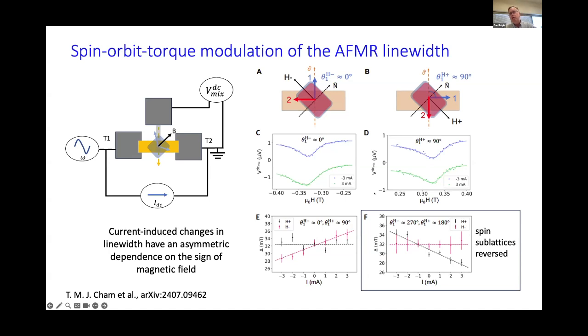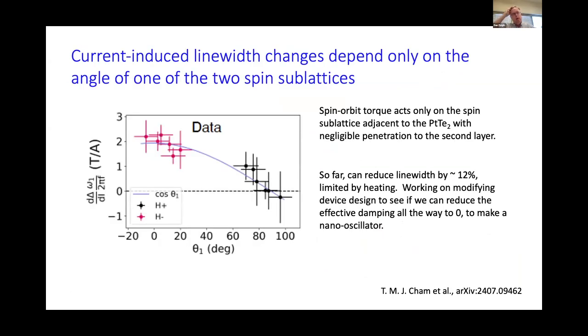And with the magnetic field, we can also switch the direction of the spin sublattices. If we do that, we see the opposite effect, the asymmetry in the magnetic field switches sign, as you'd expect from this picture. So we can look at how strong the current effect on line width is as a function of the angle of the spin sublattice adjacent to the bottom channel. There's a nice cosine dependence there, indicating essentially only that angle matters in terms of the strength of the tuning of the line width. The spin orbit torque only acts on the spin sublattice adjacent to the bottom layer.